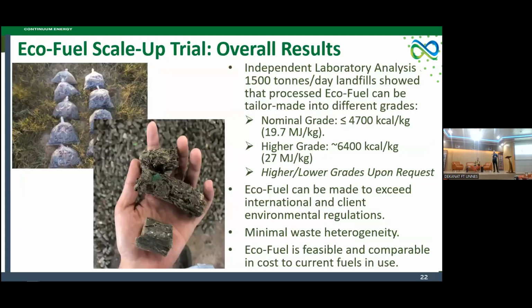Next slide. Once we separate all this material, we did independent laboratory analysis of this landfill and found that with our process, we could get 4,700 kilocalories per kilogram or even 6,400 kilocalories per kilogram. It could also get higher. Again, this is compared with conventional RDF, which can only get 3,000 kilocalories per kilogram.